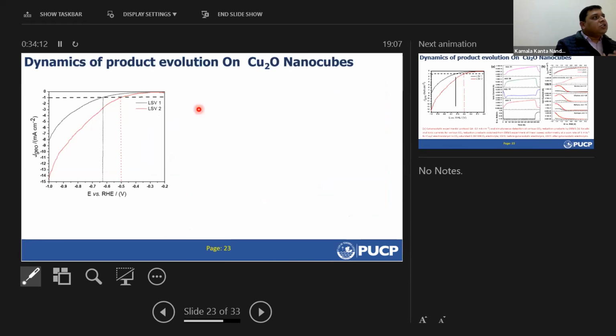And also we studied the structural evolution of copper oxide nanocubes. So what we did, we took the first linear sweep voltammetry before electrolysis. Then we performed 10 minutes of electrolysis at 10 milliampere per centimeter square. Then we recorded the second linear scan voltammetry. And this is the curve from the potentiostat. Okay. So we call it Faraday current. And Faraday current is an averaged out current. It is the current corresponding to all the processes occurring at the electrode and electrolyte interface.